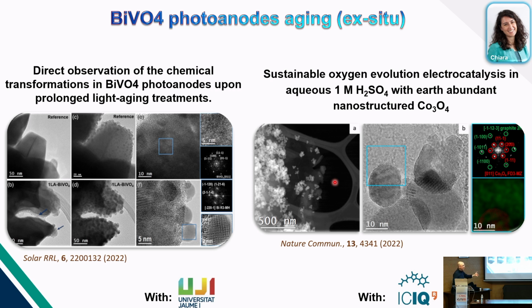So moving further, okay, now we have this multimodal. We can combine synchrotron with TEM, but now what we can do is the usual, working not in situ but ex situ. Do first analyzing the material, then performing the reaction, and then taking the material after the reaction and analyzing this. This is what we usually did without these new sample holders. So you are analyzing the material of reference before, and then in this case is after cycling, you see that the material has a lot of precipitates. In this case, it was bismuth vanadate, so the bismuth was segregated after the process. So this is something that you can do ex situ, before and after the reaction.